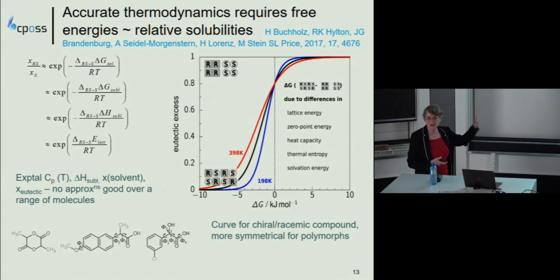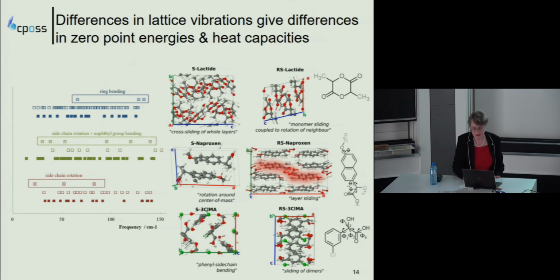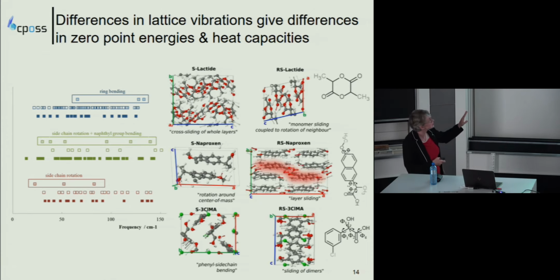Trying that out against an experimental group in Max Planck, Magdeburg, on 3 molecules, none of those approximations were good over a range of molecules. And the worrying thing is that that curve's much the same for different polymorphs. It just becomes more symmetrical when you don't have some factors of 2 in. And you can understand that from these calculations.